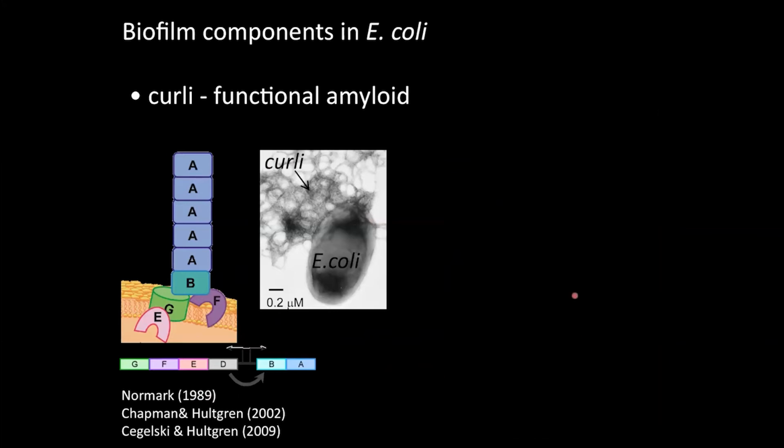And so I'll tell you about the types of biofilms of E. coli we've been studying that are really fascinating. They produce two major components, so they're not as complex as we thought, where there could be maybe 8 components. They're really two major components, polymers. And one is an amyloid fiber that bacteria produce at their cell surface. So in contrast with amyloids associated with neurodegenerative disease and Alzheimer's and Parkinson's, where protein folding goes awry, and you don't want the undesired formation of amyloids, bacteria actually harness dedicated machinery, genetic machinery and molecular machinery, to elaborate amyloid fibers at the cell surface for function, to adhere to one another.